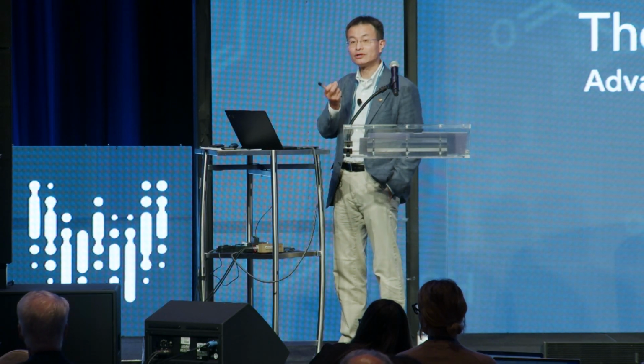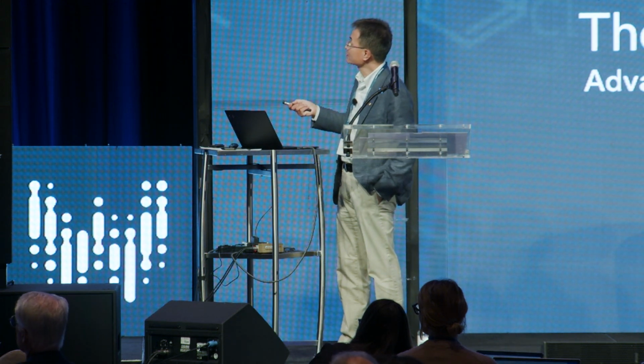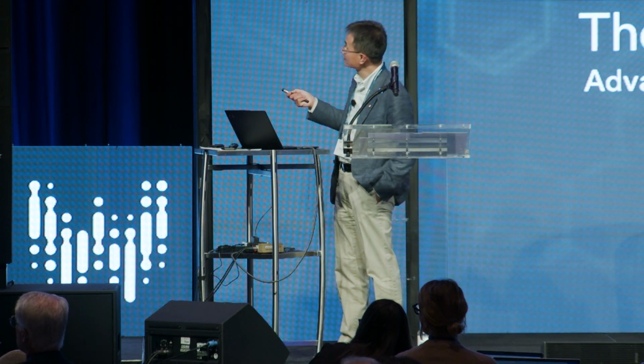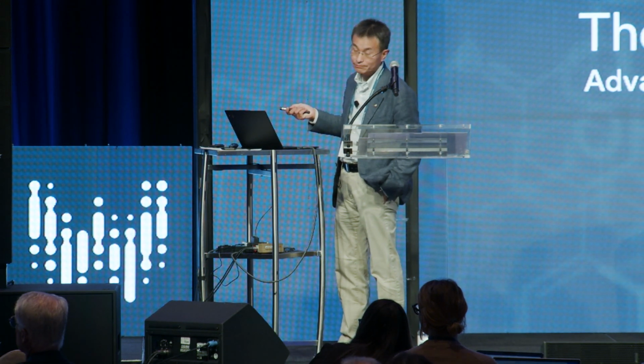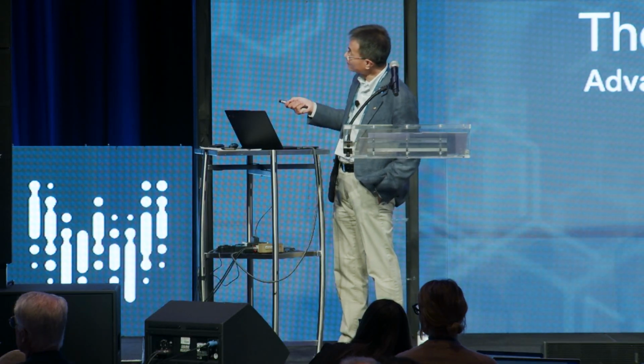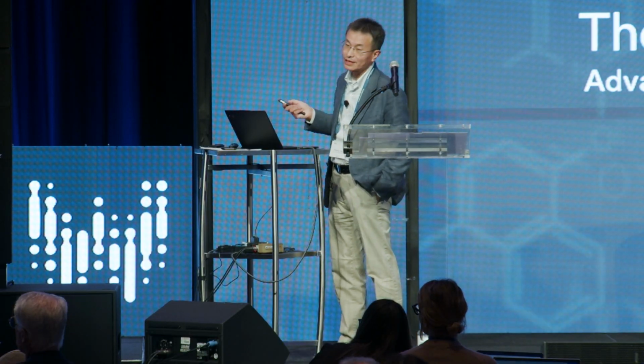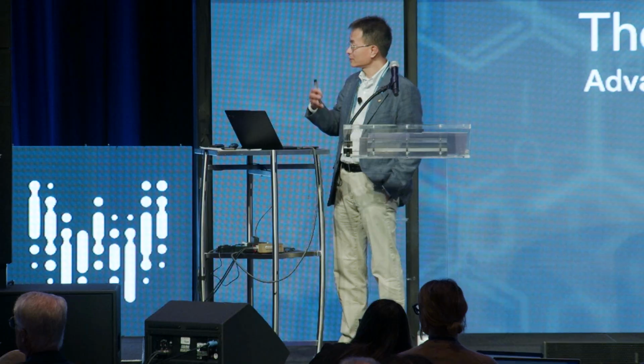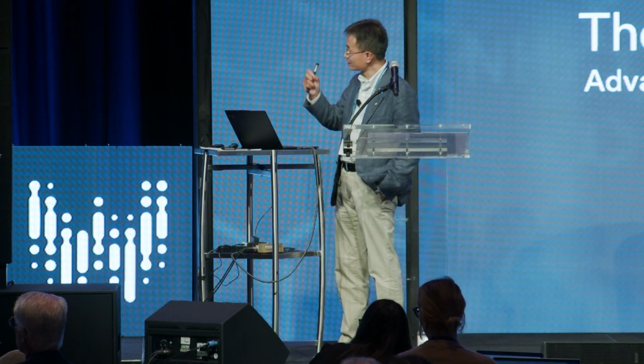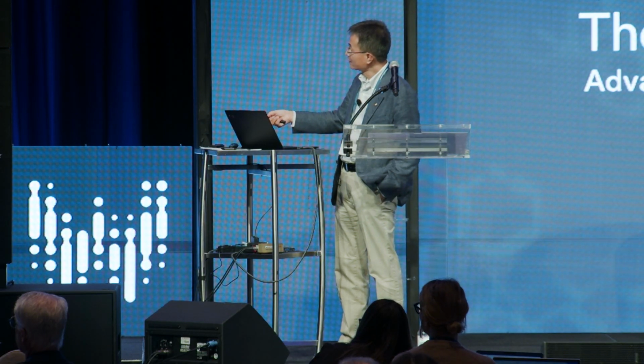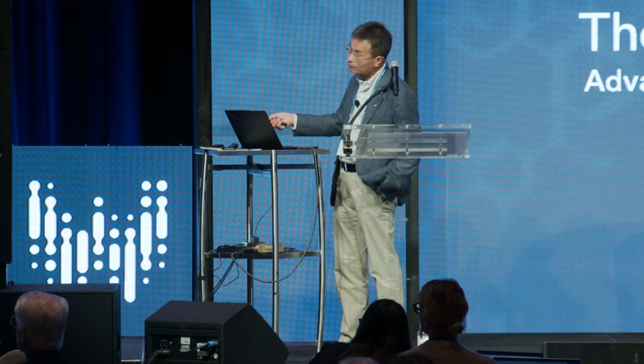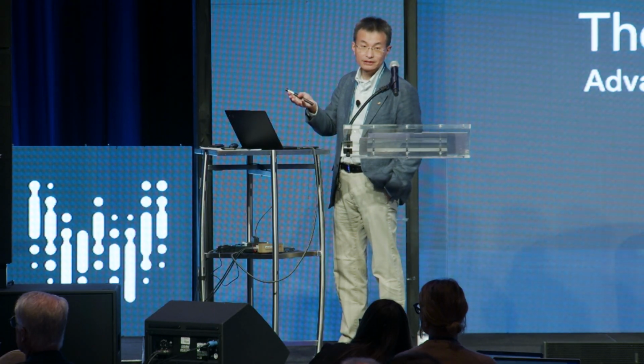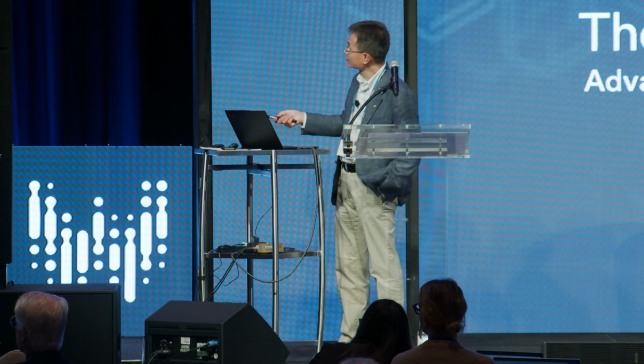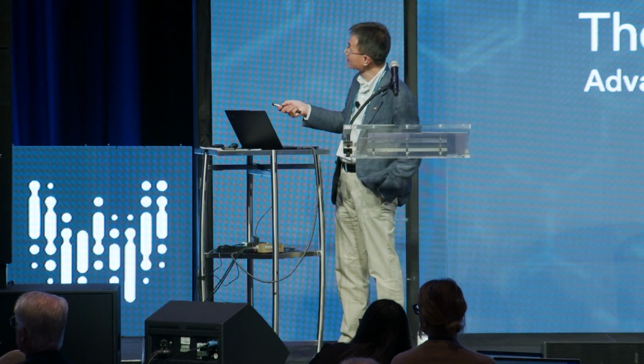Okay? This is very important in nanoscience. You need to get into the quantum confined region. This is fairly easy to do, the size control, once you understand the mechanism, because the size of these nanowires is controlled by the particle size you put in. Okay? We heard a lot about nanoparticle synthesis. You can pretty much make a very monodispersed metal nanoparticle and go into your CVD system and grow these, in this case, silicon nanowires.